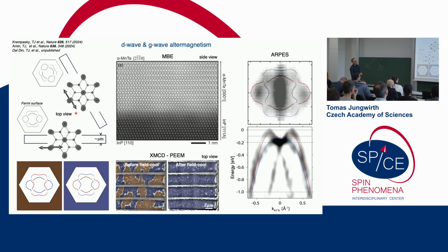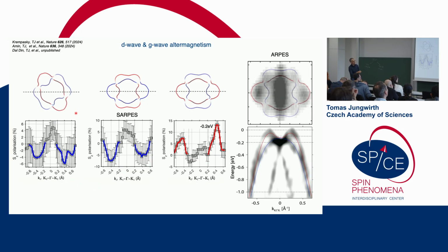So this is spin unresolved ARPES, and this is spin resolved ARPES. You basically make cuts through your Fermi surface. This is a cut at about 200 millivolts, and this is measuring in one domain. Then they time reverse the domain by opposite field cooling. And by looking at the same chip, they have patterned the bars along these 3 different directions. So it's the same measurement, the same geometry of the ARPES, which was absolutely critical, because if you change the geometry of ARPES, things change. So this is a completely consistent set of measurements where everything is controlled by the sample, not by the ARPES setup, and they see these consistent signs of the polarization.